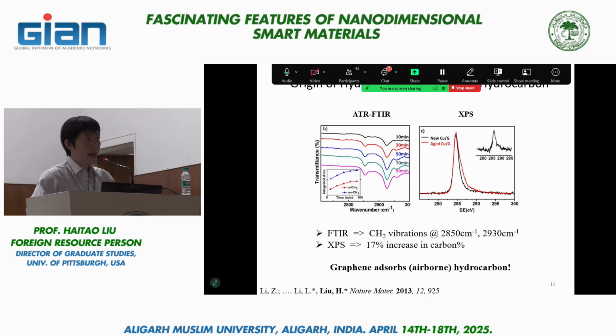Now, this was a surprise to me at that time, but once we looked into the literature, we found it's actually nothing new. There is hydrocarbon in air. They're at a very low concentration, typically on the order of parts per trillion to parts per billion. So ppb, ppm, or ppt level, very low concentration. And where do they come from? They come from all kinds of sources.